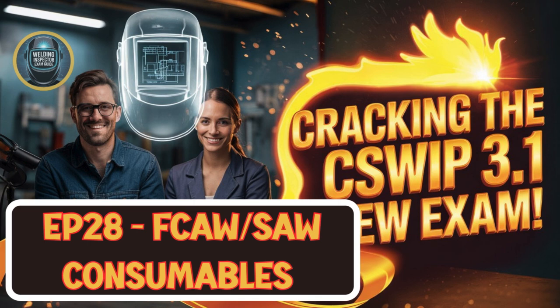Those are called gas shielded. The core contributes significantly either way. The powder also forms a protective slag covering over the cooling weld. And it can even include iron powder simply to increase productivity, basically adding more metal into the weld faster.